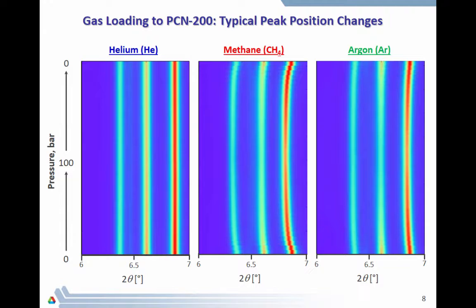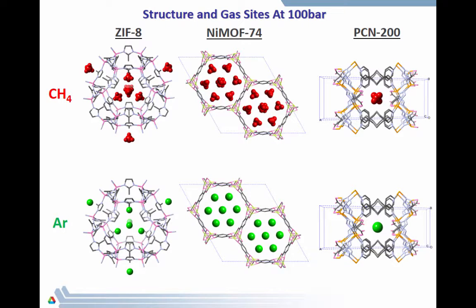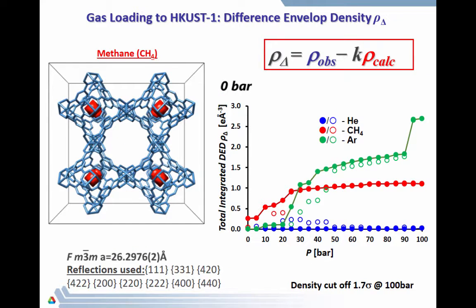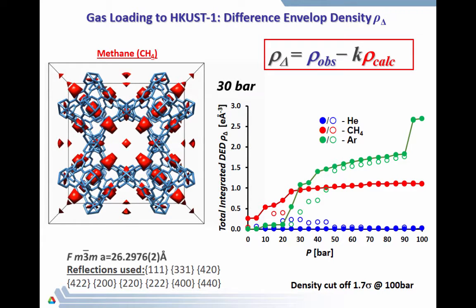But again, we are a crystallography technique, and therefore we not just can explore how the powder pattern peaks move, we can actually explore the structure, and therefore we also can determine where the gas molecules are located inside the MOFs and identify particular places and gas absorption sites inside those MOFs while you push the gas at high pressure inside them. But again, we not just can determine location, but since we are collecting this powder data all the time upon all the pressures, we can easily see how the gas molecules actually go inside the MOF pores at any particular pressure.